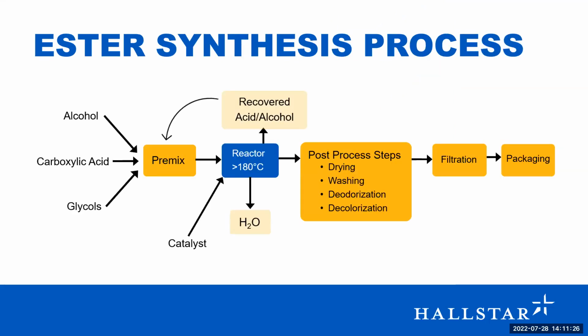The general ester synthesis pathway is to add an alcohol, carboxylic acid, and glycol to a premix tank where it would be heated and all solids melted. That's going to react at over 180 Celsius, and we're going to get water as a byproduct. We're going to have some acid and alcohols that are going to be recovered, stripped off, and recycled into our stream. So our process is a very efficient manufacturing process. Once we have our ester, be it a monoester, diester, triester, or polyester, we go through a post-drying step where we remove any excess water.